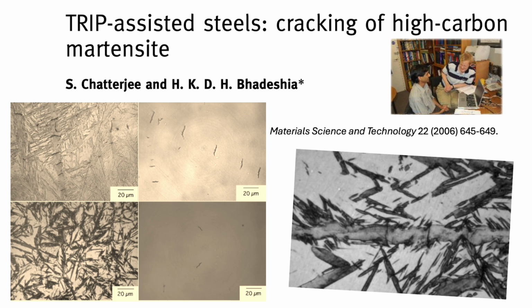They even went further and measured the spacing between cracks in the larger broken plates. And found a limit. They found a sort of minimum critical crack spacing, below which the plates just didn't seem to crack anymore. That minimum distance was around 10 micrometers. 10 microns. So keep the martensite plates below roughly 10 microns, and they're too small to easily crack themselves during quenching. That seems to be the critical threshold. Yeah, based on this work, yes. Below that size, it's incredibly difficult to get enough stress concentrated into the plate to initiate fracture.